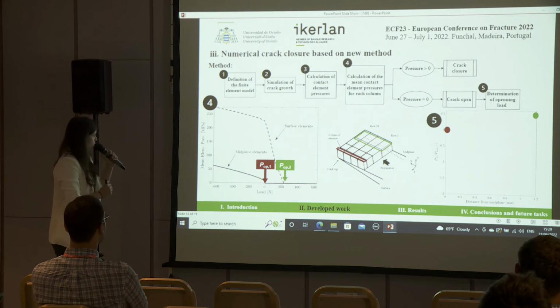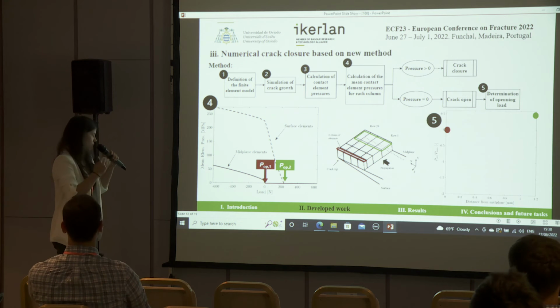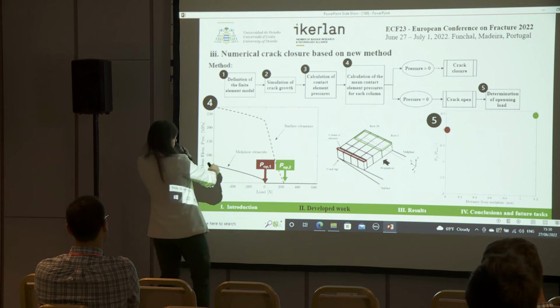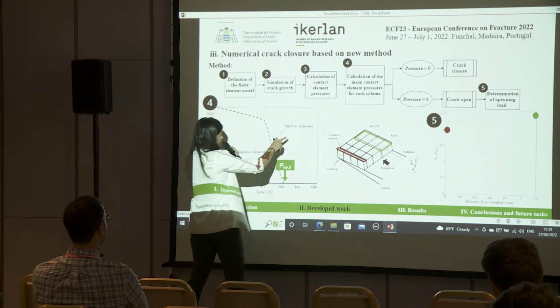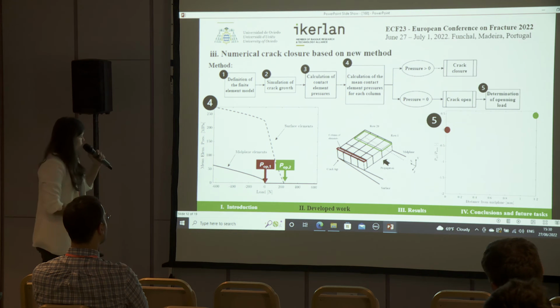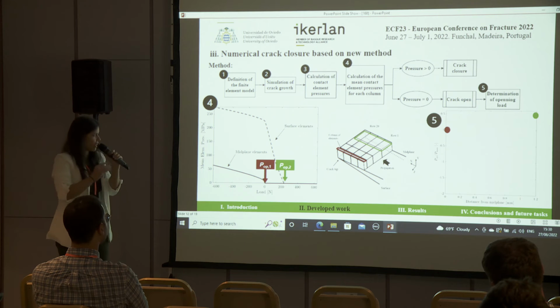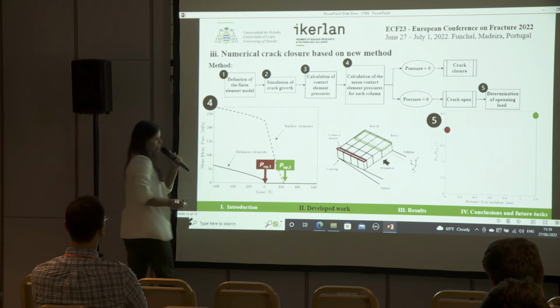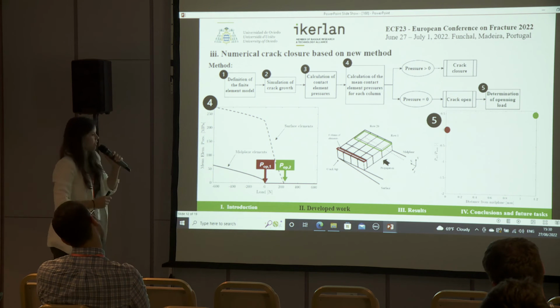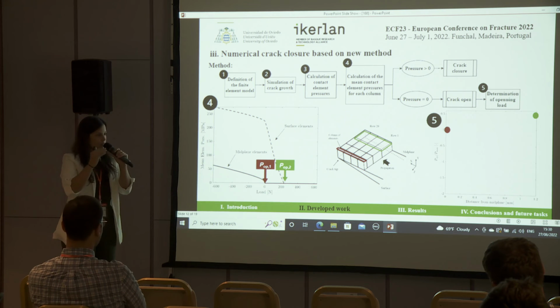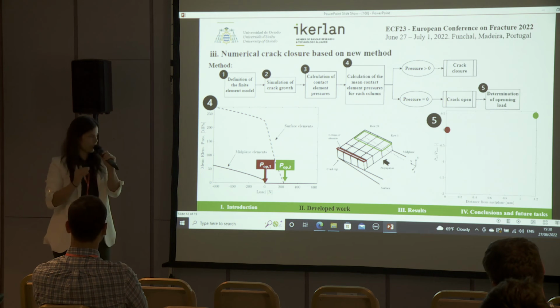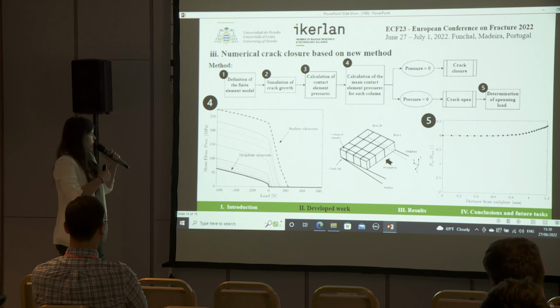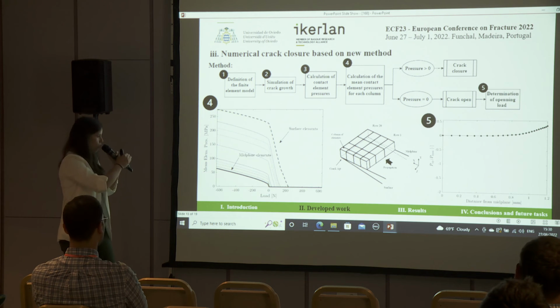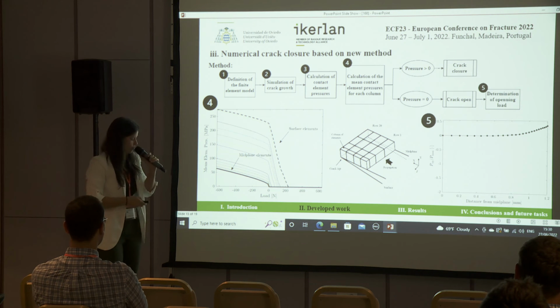Here, in the figures below, you can see again 2 examples, for a midplane column and the surface elements. Moreover, you can see here that the element pressures located on the surface elements were higher than the midplane column elements. And it's due to the size of the plastic wake generated during the crack propagation. So again, reproducing this procedure for all columns through a thickness, we have here the peak distribution through a thickness.